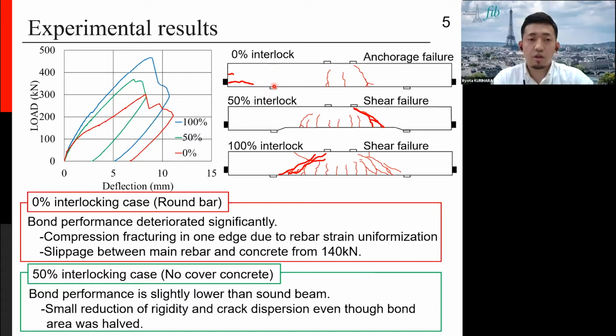In the 0% case, a round bar is used as the main rebar, but with no treatment of the rebar surface, so the chemical and friction action exist, I think. And in the 50% and the 100% cases, the same deformed bar was used. So the difference is only the contact area between rebar and concrete.